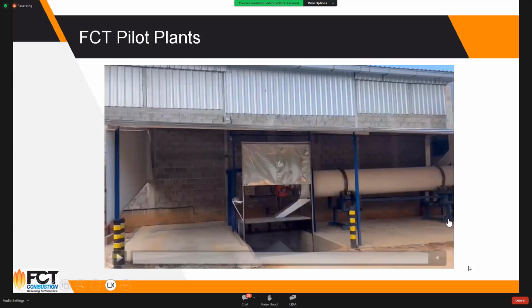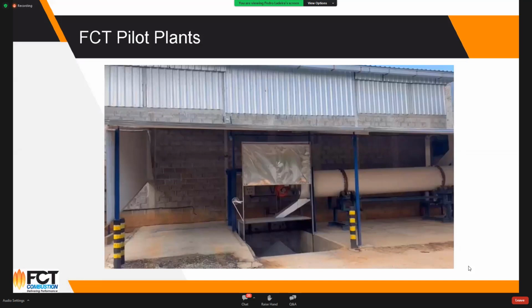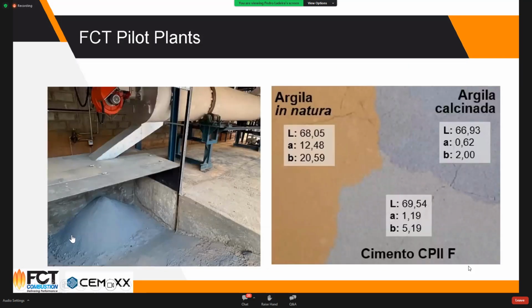This one had a very high iron content, over say 15% of iron oxide in the raw material, and we managed to get the gray color despite oxidizing conditions in the kiln and not using water, not using any special fuel to do that. And the product becomes like this, and when we go from the original clay into the calcined clay and the cement afterwards, you can see very low a* numbers, which we use to measure color in terms of red.